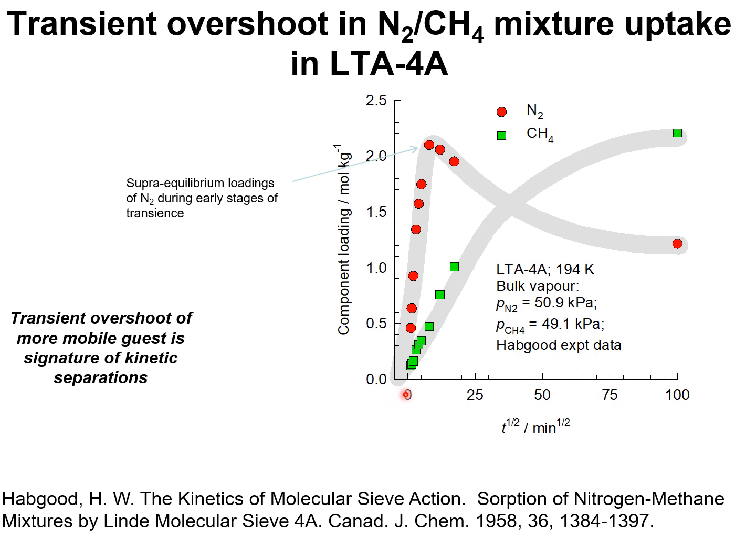The cycle times can be adjusted to be short enough such that the adsorbed phase is richer in nitrogen, and the more poorly adsorbed methane is rejected into the gas phase and recovered at the exit of the fixed bed adsorber.